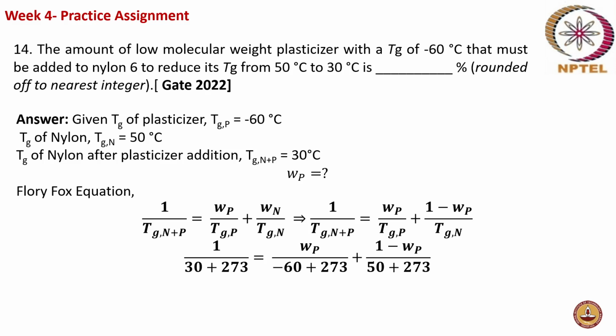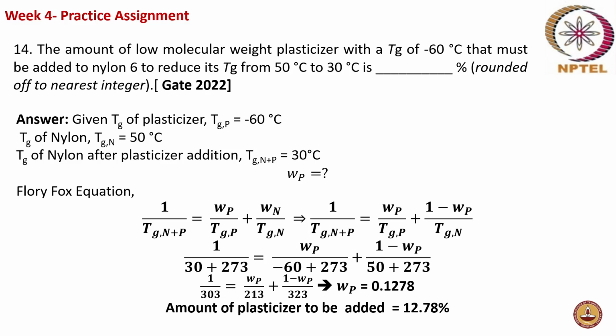You said you have to convert the temperatures to Kelvin. That's what is done, so you are right. First, converting the temperature to Kelvin: the final glass transition of nylon with plasticizer is 30 plus 273. So 1 by (30 plus 273) is equal to Wp by (minus 60 plus 273) plus (1 minus Wp) by the glass transition of nylon, 50 plus 273. So you end up with 1 by 303 equal to Wp by 213 plus (1 minus Wp) by 323. When you do the mathematics, you get Wp as 0.1278. Converting into percentage, the amount of plasticizer to be added is 12.78% to reduce nylon's glass transition from 50 to 30 degrees.